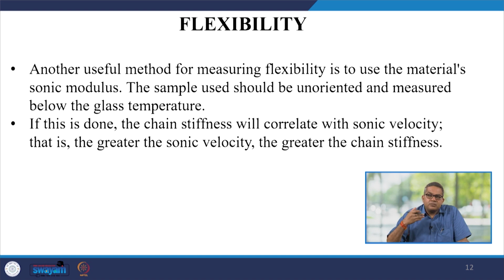The sample used should be unoriented, measured below the glass transition temperature. If it is done, the chain stiffness will correlate with the sonic velocity, that is, the greater the velocity, the greater the chain stiffness.